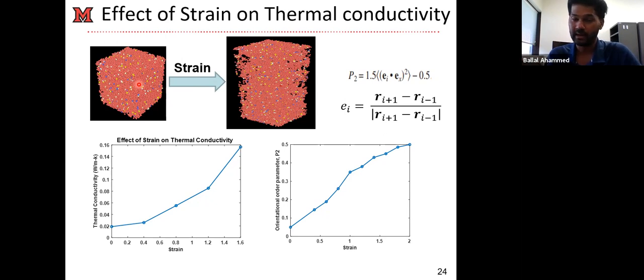So it reduces the heat transport. If we can strain the material and give the polymer chains a chance to be somehow straightened, it would help to improve the thermal properties. So we applied strain in the material and recorded the thermal conductivity. We found that when we apply the strain, the thermal conductivity increases by some degree, which is a good sign. That means the hypothesis is working. So then we proved that it is related to the straightness of the polymer chains.